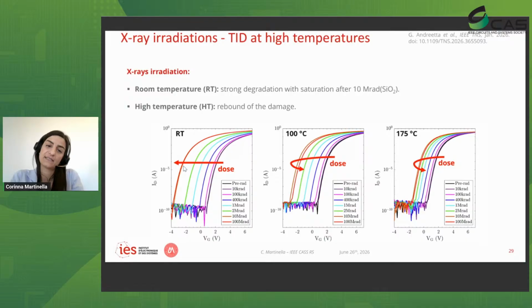When we are instead irradiated at 100 degrees C, what we start to observe is a rebound of this effect. So between 10 megarad and 100 megarad, we see a rebound of the effect, and so a shift towards the right for the last point here. And similarly, when we are irradiating at 175 C, with also an overall lower degradation.